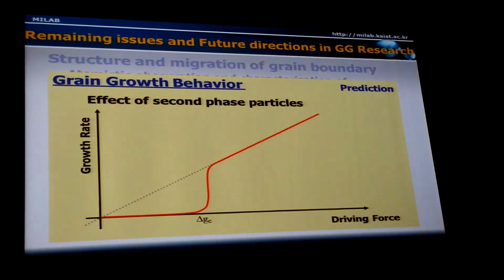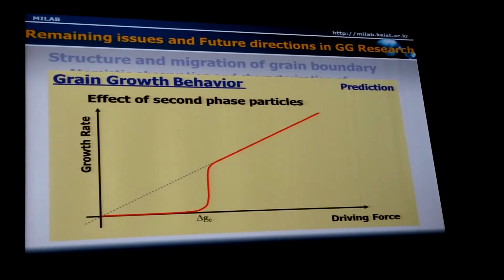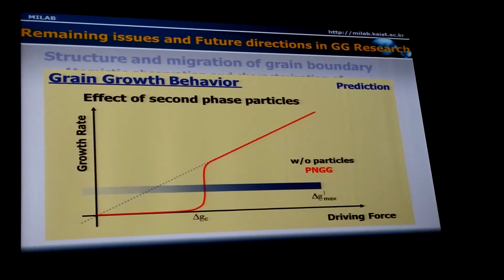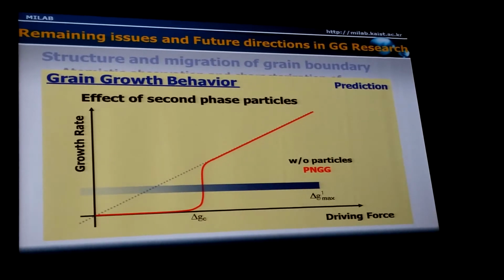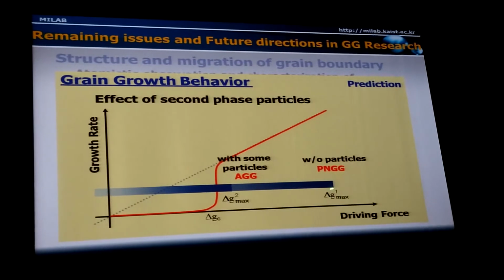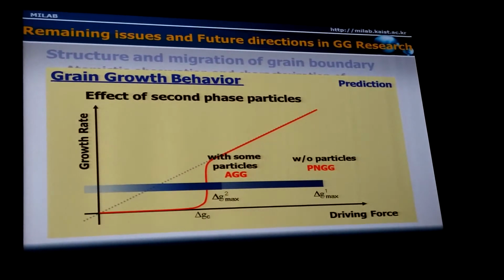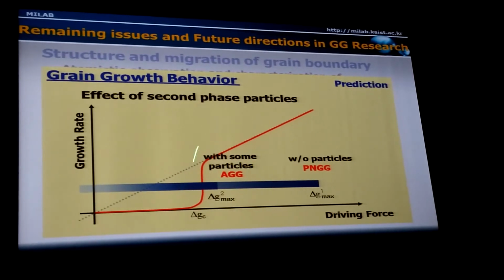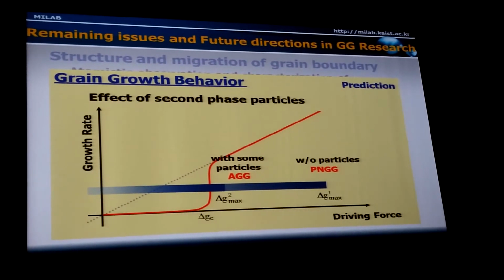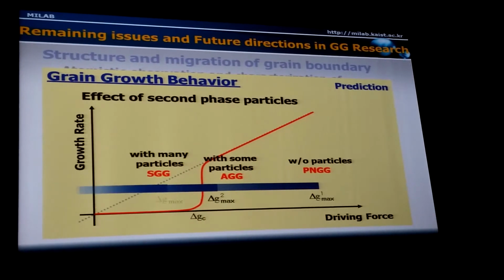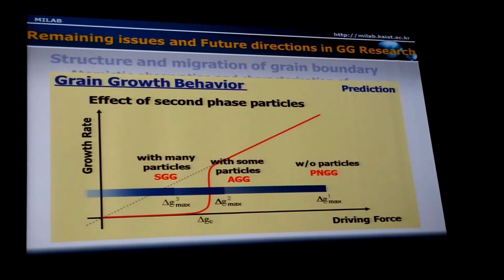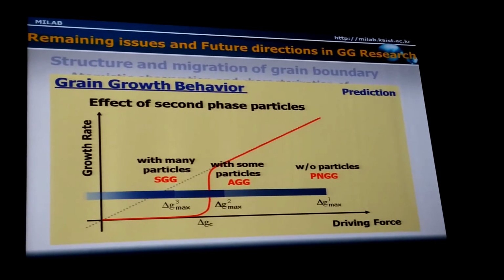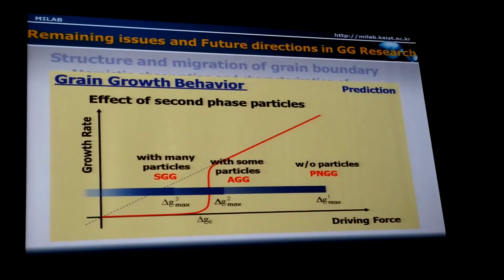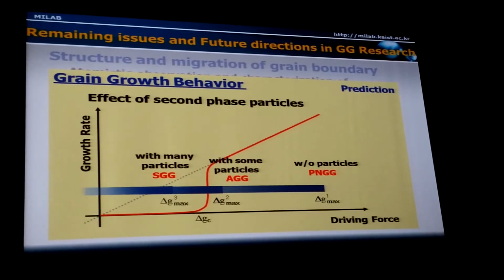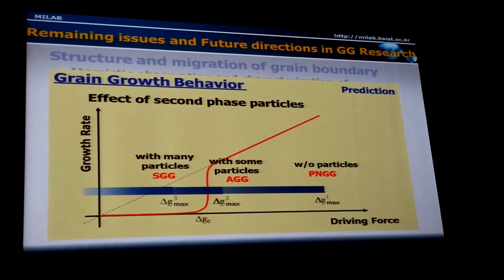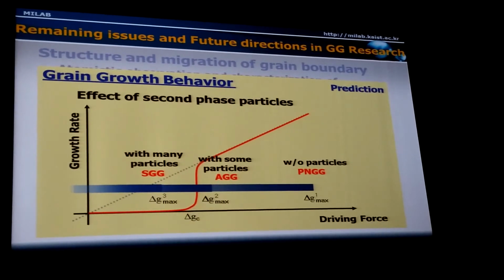And then in the case of grain growth, we may do a model experiment of the effect of second phase particles. If there are no second phase particles, grain growth behavior would be quite normal, but if there are some second phase particles, maximum driving force will be reduced because of the drag of the second phase particles. In that case, we will be able to observe abnormal grain growth. And if the fraction of second phase particles is further increased, then grain growth will not occur, stagnant grain growth. This is a prediction based on the mixed control of grain growth. So I think such a model experiment would also be helpful to support or to confirm our model and mechanism of mixed control.